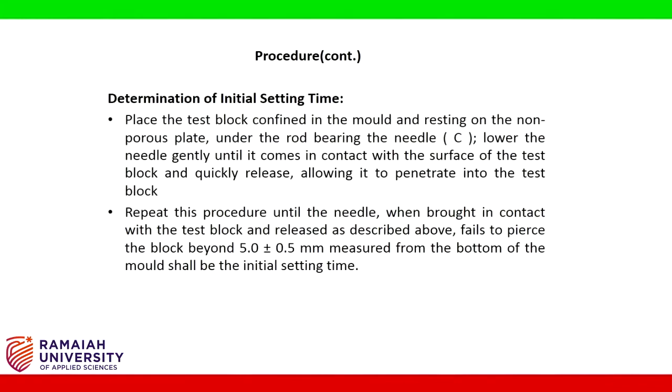Determination of initial setting time. Place the test block confined in the mold and resting on the non-porous plate under the rod bearing the needle C. Lower the needle gently until it comes in contact with the surface of the test block and quickly release, allowing it to penetrate into the test block.